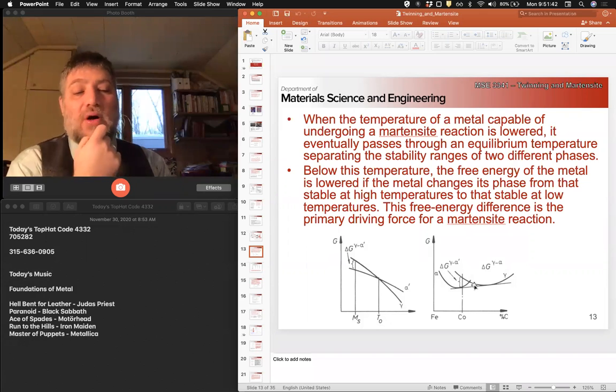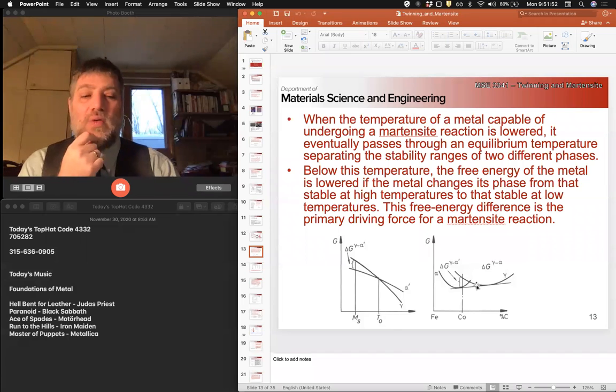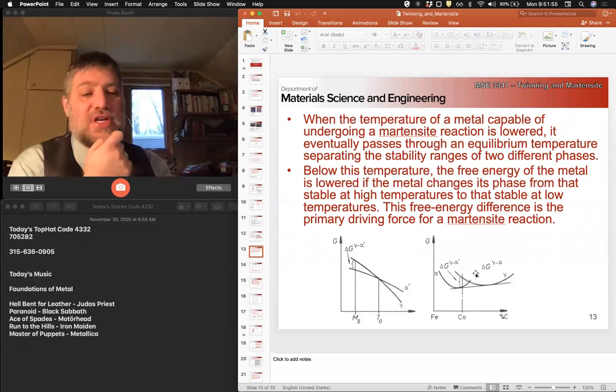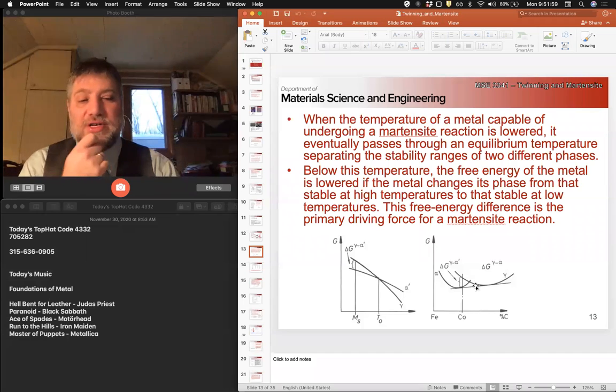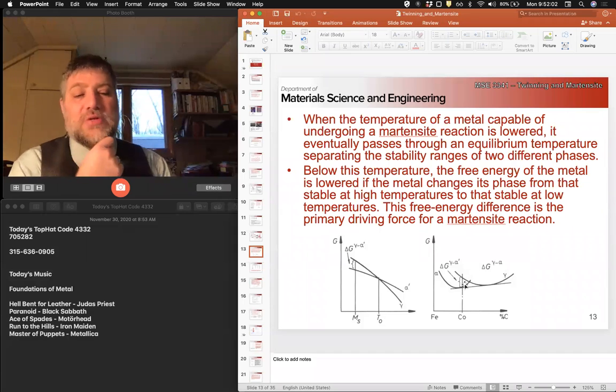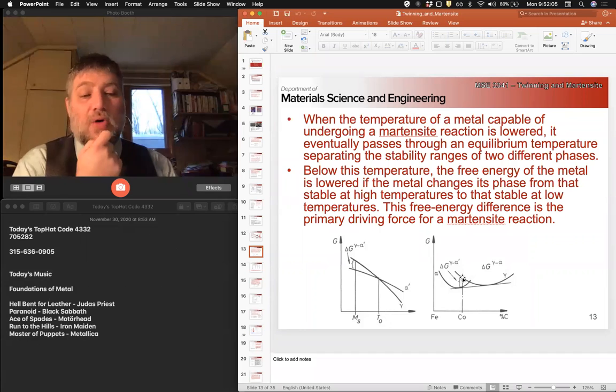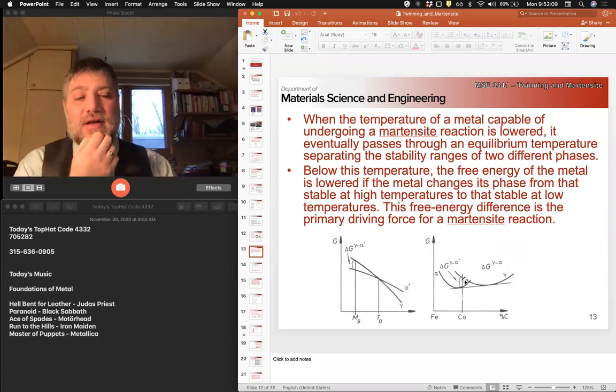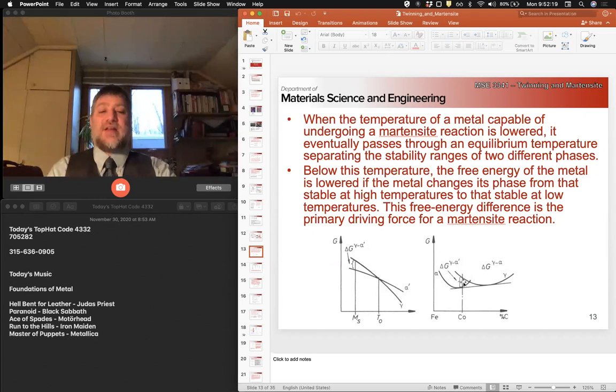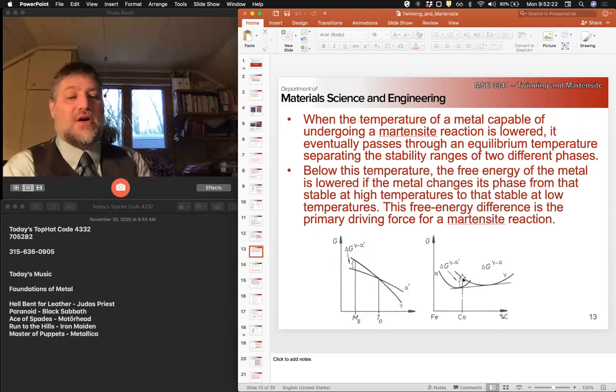We cannot transform directly from gamma to alpha at this composition by a martensitic reaction because the free energy of alpha is higher, right? So without long-range diffusion, we can't lower our free energy. The transformation will only raise it. But once we're past this intersection point, we can locally lower our free energy by going directly from gamma to alpha at the same composition, right? So if we're to the left of this intersection point, we don't have an activation barrier that we have to overcome. We don't have an energy penalty that we have to pay by nucleation. Okay?